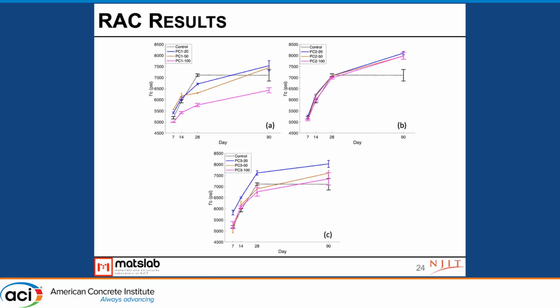And for the second group, one of the interesting findings was that there actually wasn't a very noticeable effect at all of increasing RCA percentages on the strength of the system, which is in contrast to what you would expect. Usually you'd expect that no matter what, if you go from 20 to 100% replacement, your strength would be significantly reduced. And then for the PC3, we're seeing not necessarily an increase or a decrease, but a little